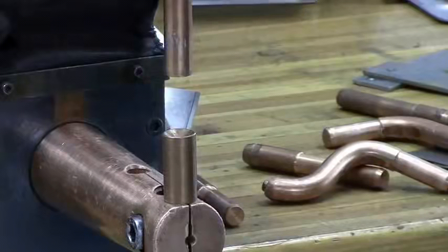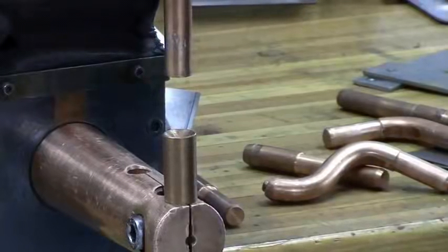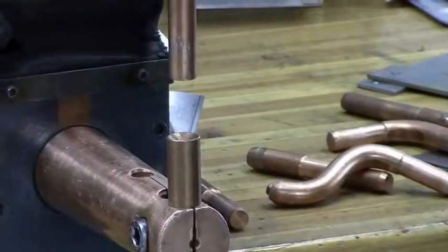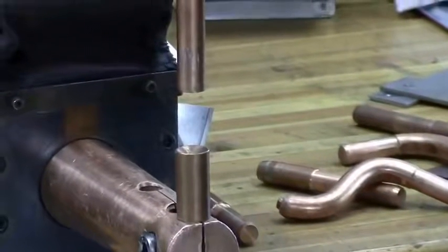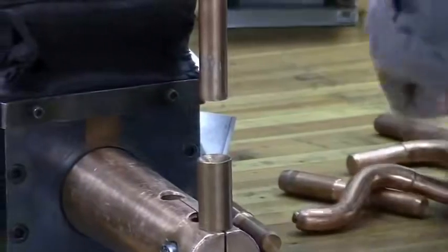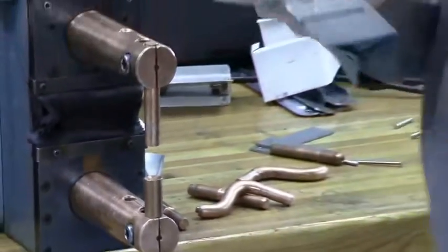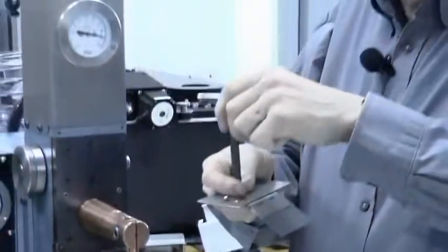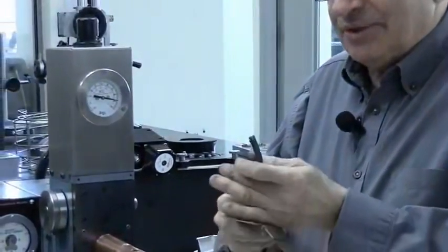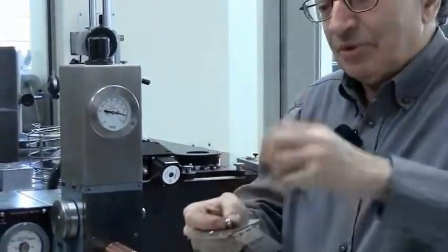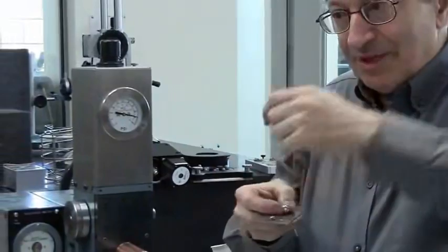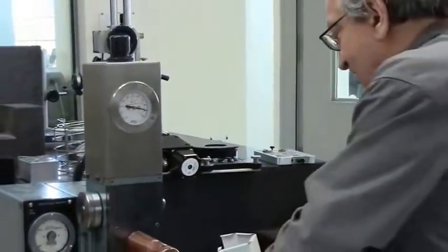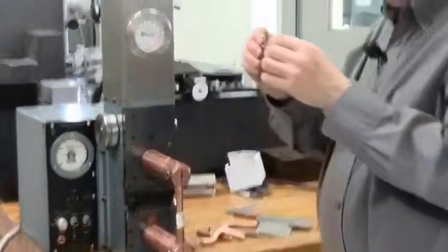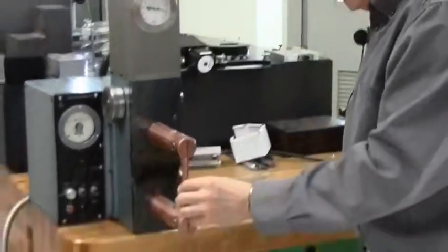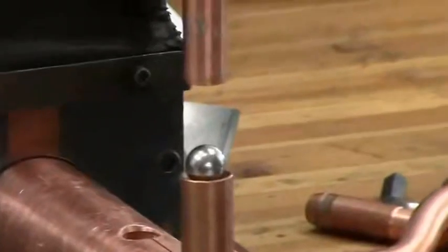Now because balls are very cheap and very accurate, you can take advantage of them in all kinds of adjustments, like for example arms which have to move in all directions. So for example, if I wanted to make an adjustment where I have a rod which I can move in any direction and lock, the easiest way to do that adjustment is to weld a ball at the end of the rod, put a washer over it with 2 screws which clamps the ball down, and then I can lock it. Okay, so for this I need to weld a ball at the end of a rod, and for that I put the ball in a conical hole, and I have a special collet adapter to grip the rod.